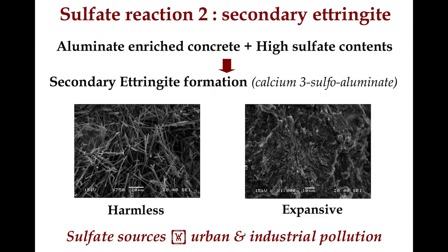So the sulfate reaction 2 is the formation of secondary ettringite. So the aluminate-enriched concrete plus high sulfate contents give the formation of secondary ettringite. So we have two possibilities. When ettringite is well crystallized in needles, like you can see here, it's harmless. But when ettringite is badly crystallized, like here, it can generate expansion. So sulfate sources are mainly urban and industrial pollution.